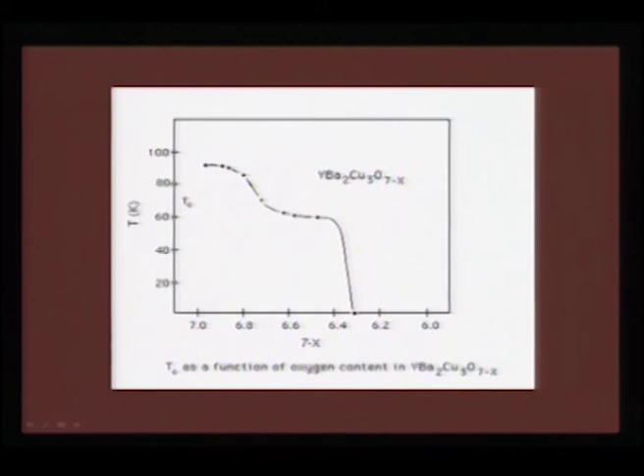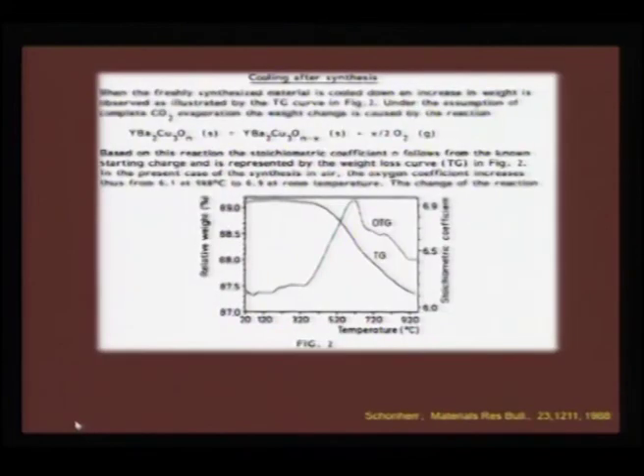As you would see here, this 7 minus x or 7 minus delta is very critical, because as you vary from 7 down to 6.5 according to the stoichiometry, you can also see how the Tc drops to a non superconducting state. When it is a superconductor, you can clearly get a 90 Kelvin Tc, and that is nearly a fully oxygenated compound. Okay. So, where does this oxygen go? That we can see from the crystal lattice if we take a closer look at it.